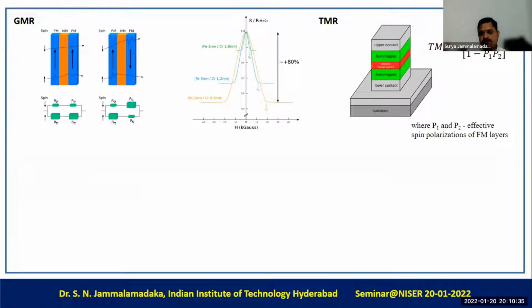Later, tunnel magnetoresistive devices were developed. In tunnel magnetoresistive devices, between the two ferromagnetic layers, the non-magnetic metal has been replaced with oxide materials. A huge amount of tunnel magnetoresistance has been achieved, but people were able to achieve only so much. To improve the tunnel magnetoresistance of the device, the spin polarization of the material must be very high. If we can have a material with 100% spin polarization, a large tunnel magnetoresistance can be achieved. So in this direction, a lot of research is going on and a lot of materials are being developed, which I'm going to discuss in today's lecture.